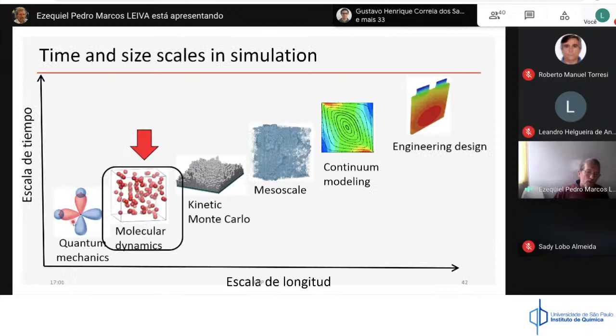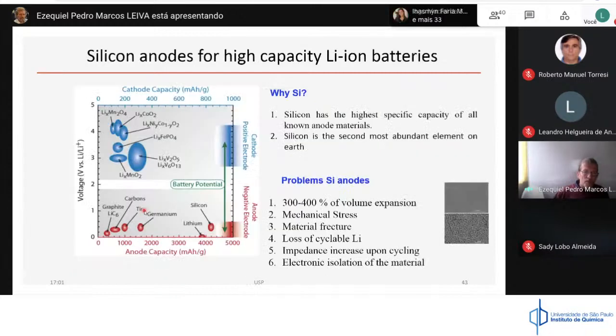We go one step up in the computer simulation of different systems, and we go to molecular dynamics, another tool to investigate processes in lithium-ion batteries. You have probably read that silicon anodes are very promising for lithium-ion batteries. If you look at voltage and capacity on this scale, you will see that graphite is at 370 something milliamp-hours per gram, which is relatively small. But if you look at different materials, you will find that silicon has a very high anode capacity. That's why silicon was considered a much better candidate than graphite.